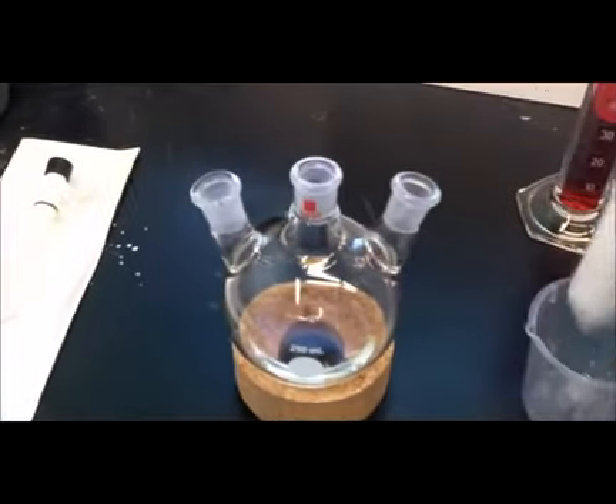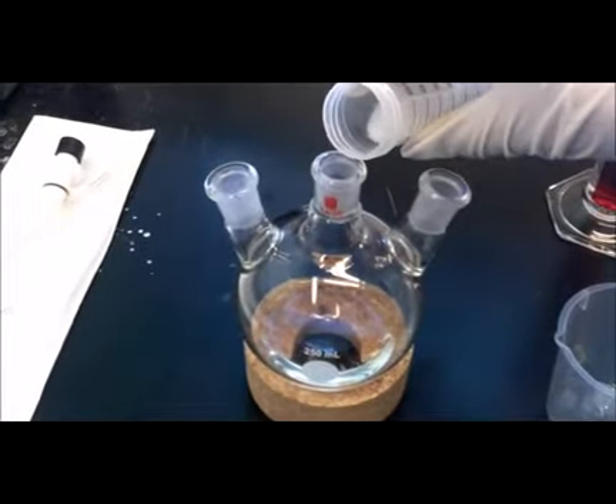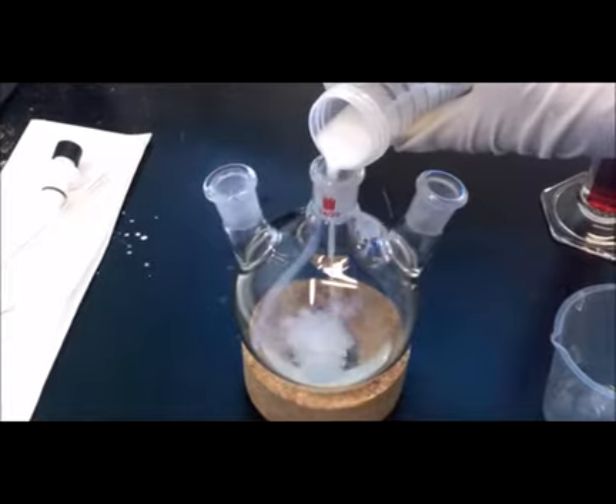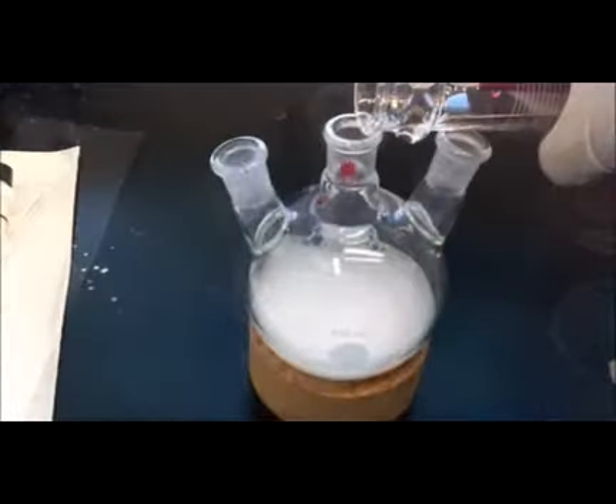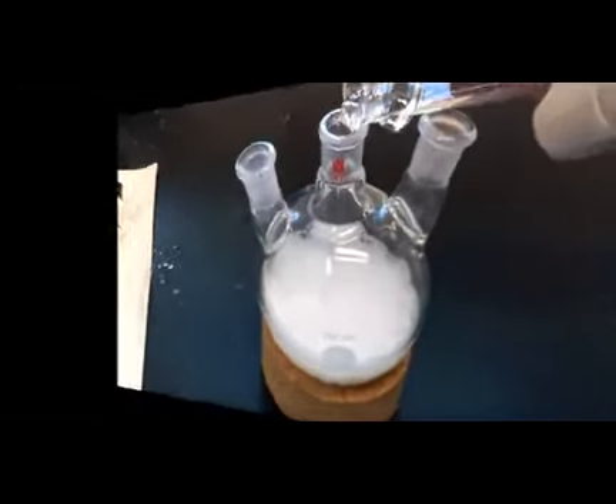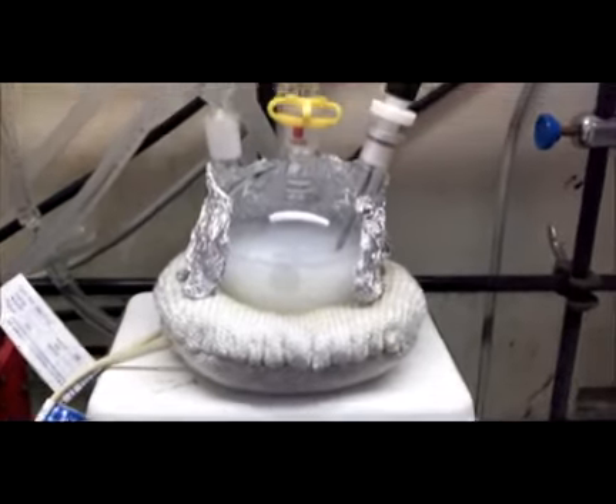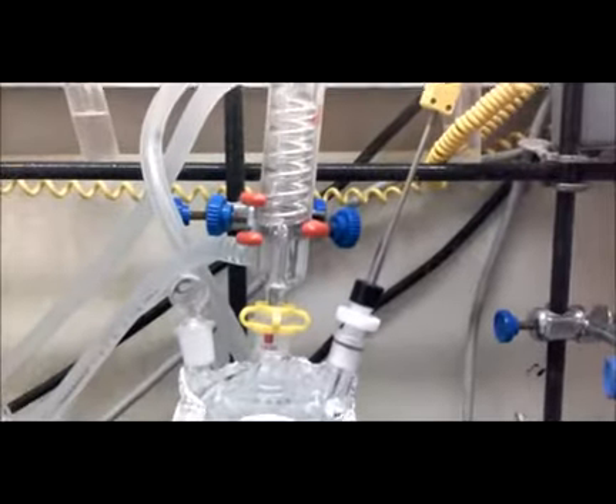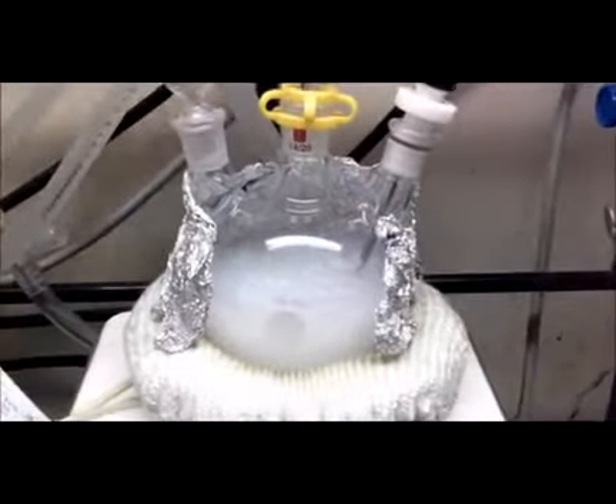After the titania is completely dispersed, we pour it into the RBF with the lithium hydroxide and add the rest of the 150 ml of water. We then put the RBF in the reflux condenser and let it stir at 600 rpm. We reflux it at 100 degrees Celsius for an hour and 15 minutes.